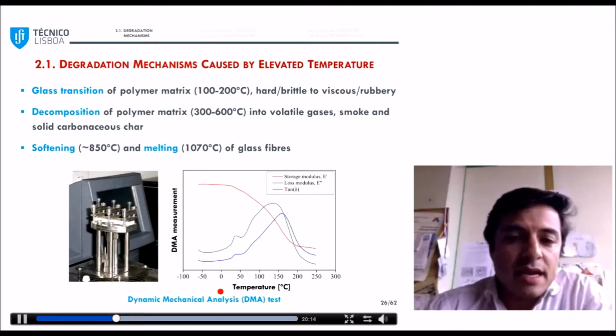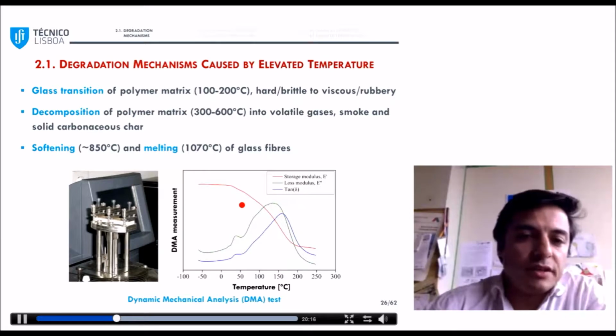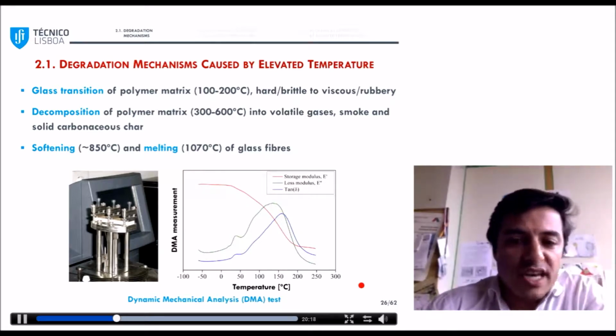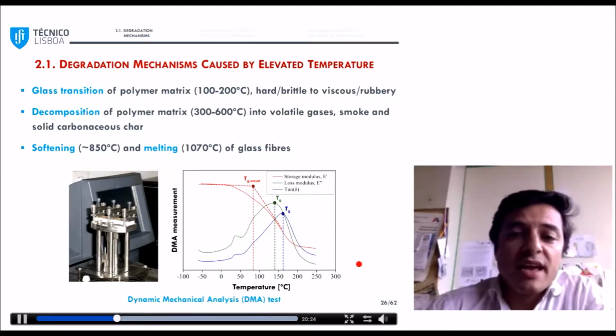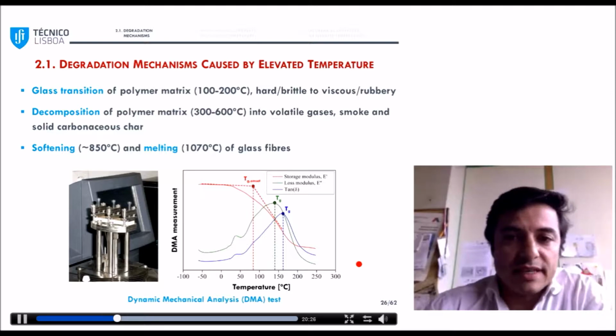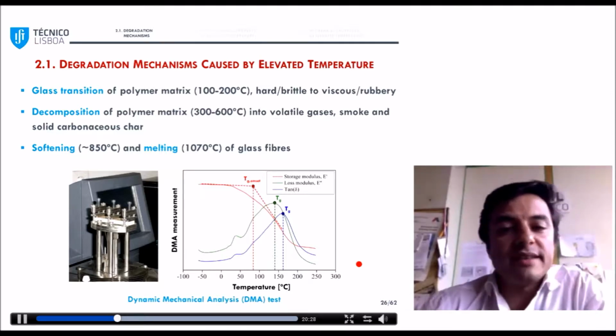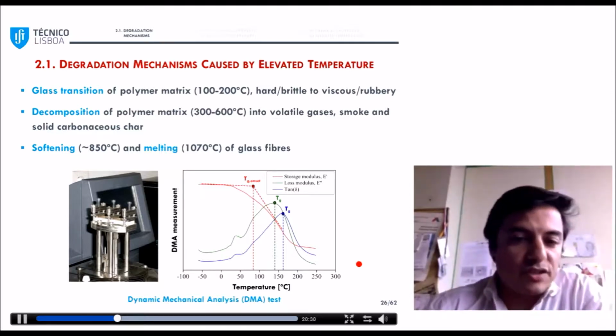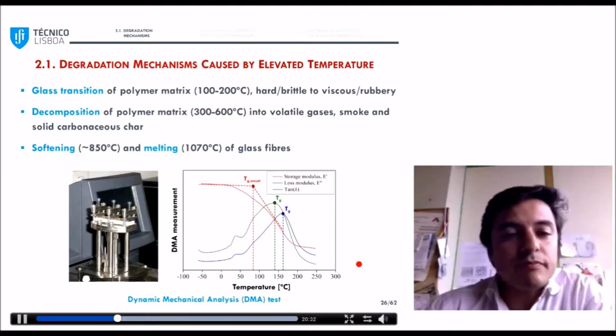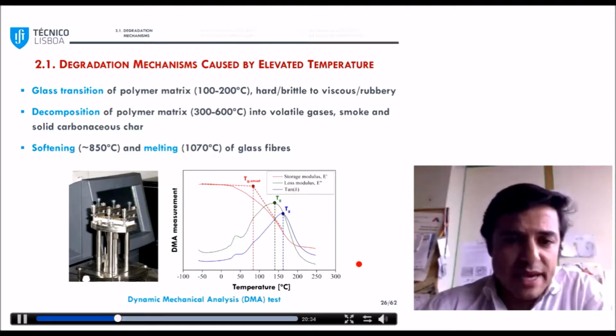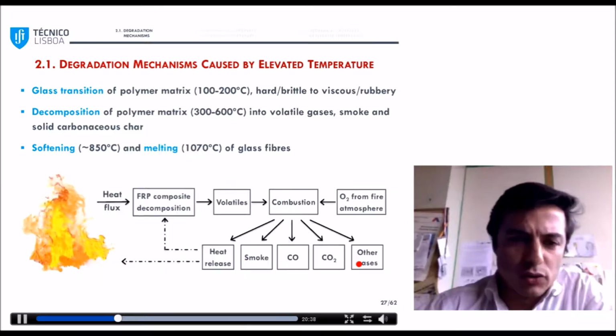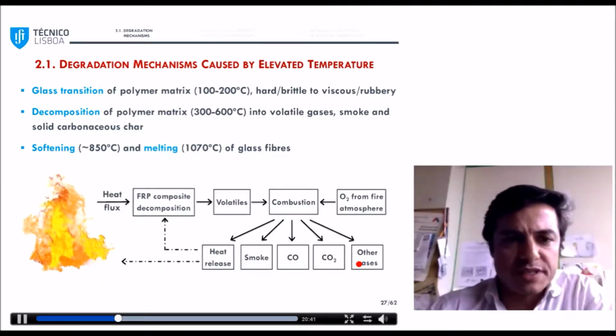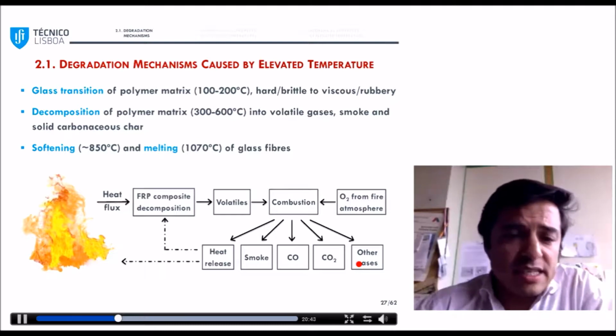One of the most common are DMA tests, which provide, as you see here in the outputs, the change with temperature of three parameters: the storage and loss moduli, and the tangent of delta. And any of them provide an estimate of the glass transition temperature, or Tg. You will see next the effect that this process has on the material properties.